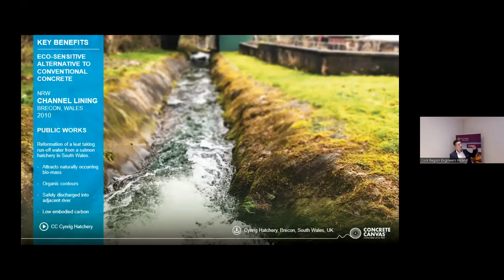But just keep in mind that a GCCM product has a very low alkaline reserve, and it also has a very low washout rate. So typically it doesn't affect the pH levels in the water once you've installed and hydrated the material. For that reason, it's been approved by the EPA, the Environment Agency, and in this slide here, the Natural Resources Wales in the UK, where they directly installed the material for this salmon hatchery plant for ditch lining. And you'll notice on this slide that there's algae and moss buildup on that hydrophilic top surface. While it's still preventing any root-growing vegetation coming through the material, it will have a buildup and mossing effect, so it will blend in better over the long term.